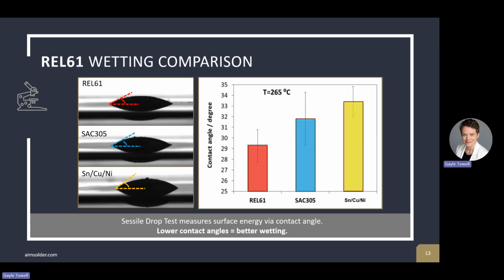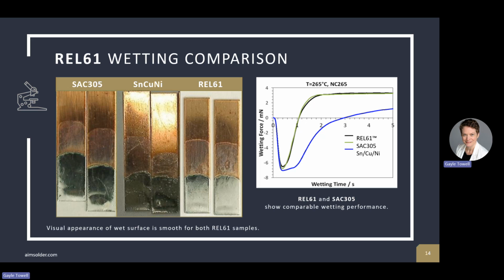REL61 also wets very well. This is a wetting comparison where we measure the contact angle of a molten drop. The smaller the angle indicates better wetting, and REL61 had the smallest of the angles measured. This is another wetting comparison where we look at wetting force over time. And in this particular test, we see that REL61 is comparable to SAC305.